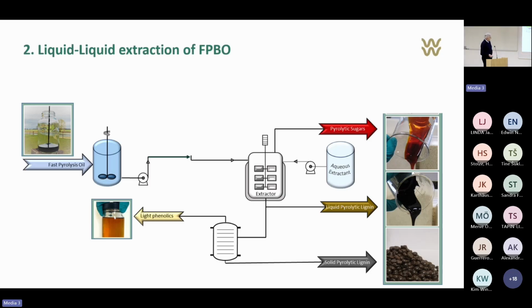Normally what we do, and that's also what we did here in this project, is start with fast pyrolysis, then have a liquid extraction with an aqueous extractant, water. We get a separation between sugars and lignin. What's mentioned here is the liquid pyrolytic lignin. That's the first product, but in many cases the solid version is preferred.